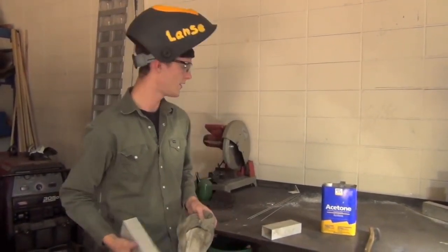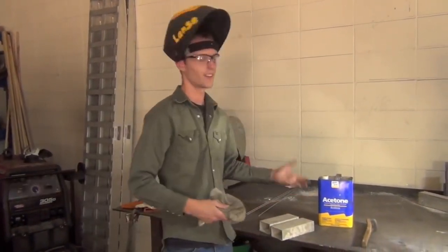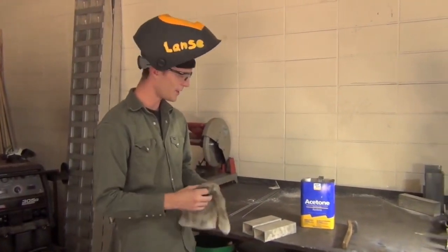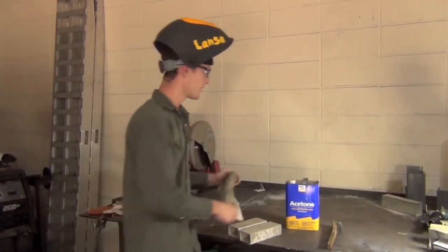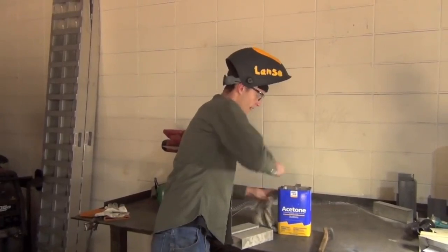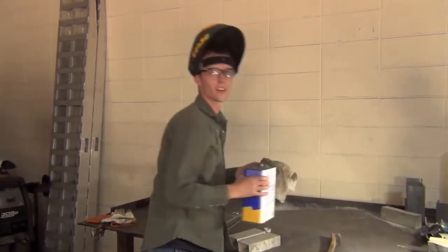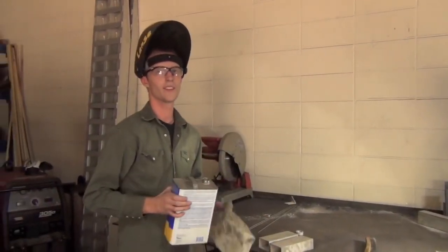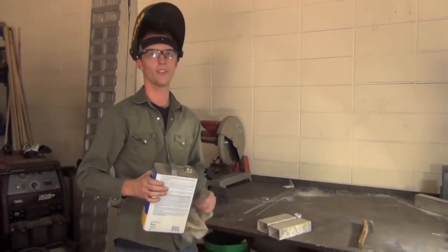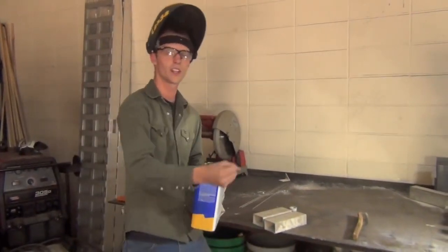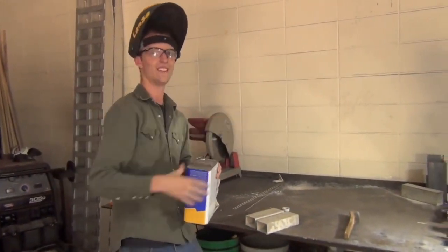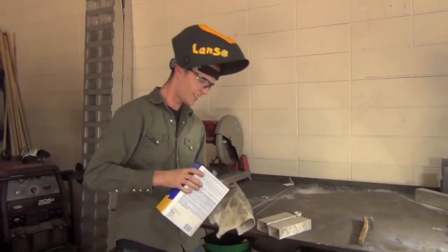But the way I'm going to clean this here is with some acetone. This is a very popular method, and a rag. And then I'm going to take a stainless steel wire brush to it. Now, one thing to keep in mind is if you're going to do both of these things, you might want to do the acetone first and remove the crap on the surface, because otherwise when you hit it with the brush, you end up pushing that stuff into the aluminum, and it's not a good time.